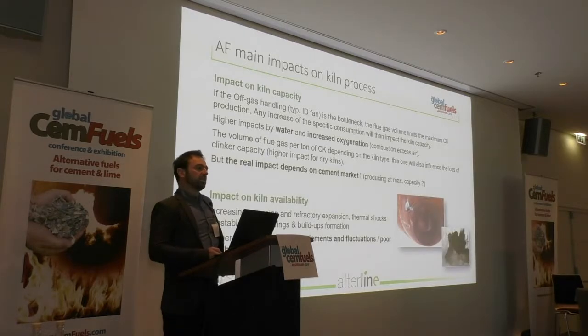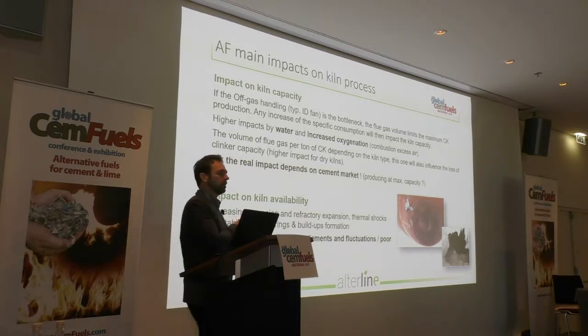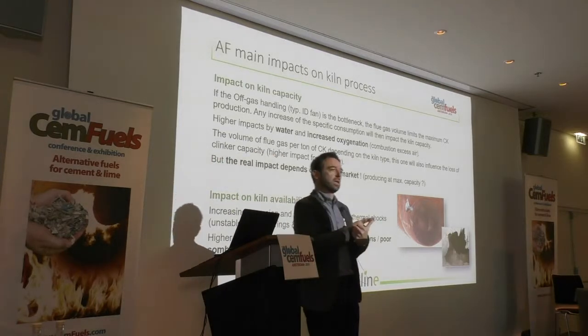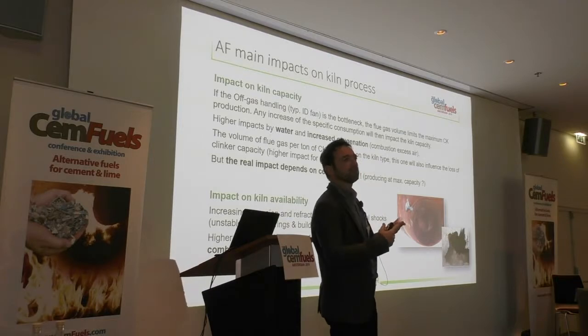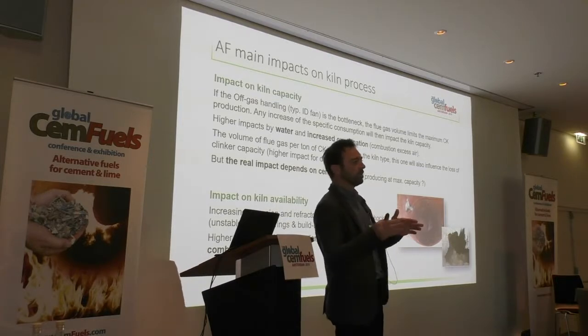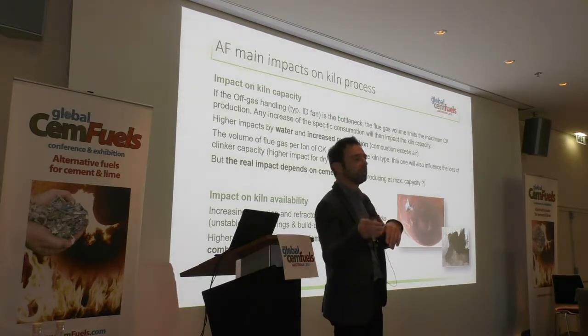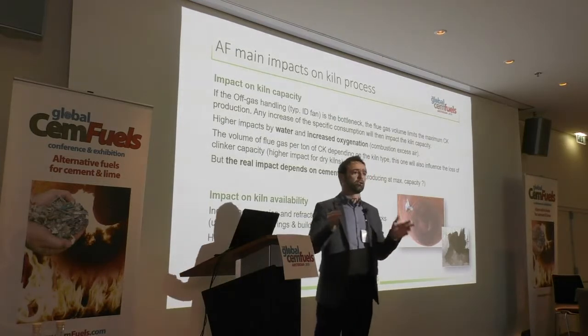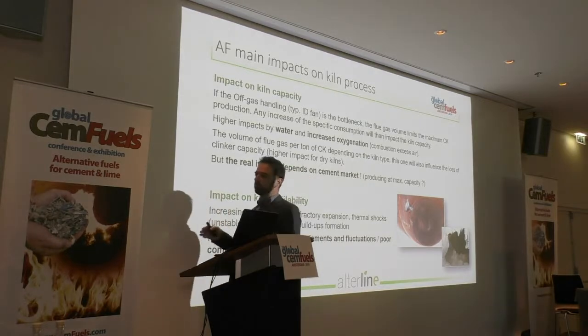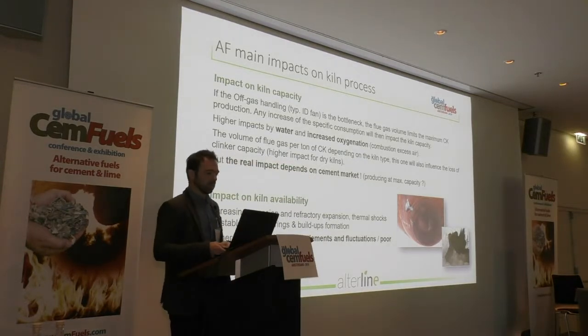The impact on the kiln availability, basically maintenance, like corrosion problems, refractory expansions, and on the other hand, due to the chlorine increase, more buildups, less stable coating, so risk of falling. Globally, you need to increase the maintenance.